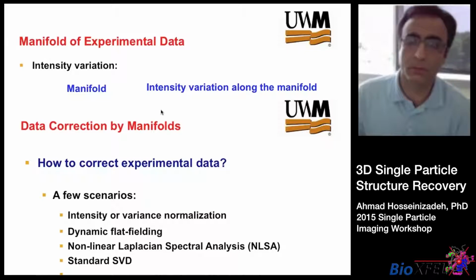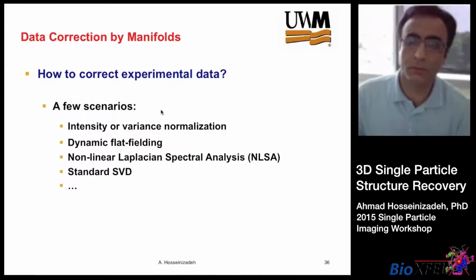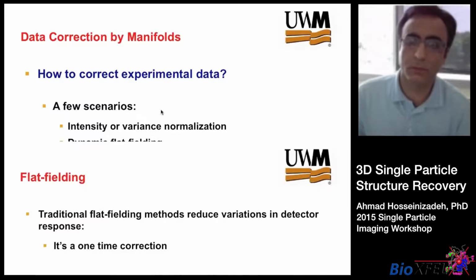The traditional flat fielding methods reduce variations in detector response, and they are just a one-time correction for all data. But here, in the case of XFEL, stochastic effects change from shot to shot. So this means that we require a different flat field for each diffraction pattern.